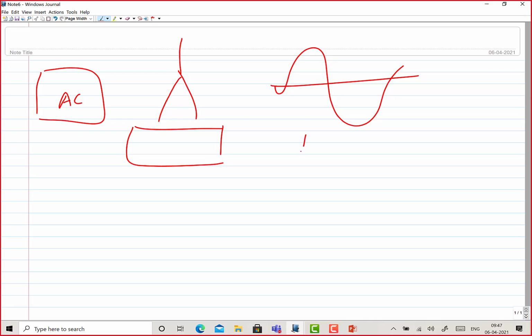It means arc stability is low in AC, and there is no control over heat, because heat generation is equal on both sides. While in DC welding with DCEN, the electrode generates less heat and the base metal side more heat. That can be used favorably for achieving the desired penetration and weld size.